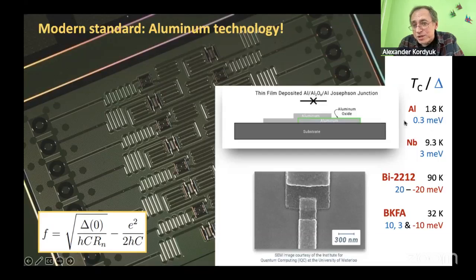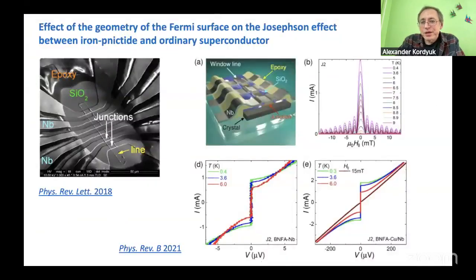In aluminum, the gap is 0.3 millielectron volts. And in cuprates, it could be 2 orders of magnitude higher. And of course, it would be very appealing. And one of our interesting results was to try.